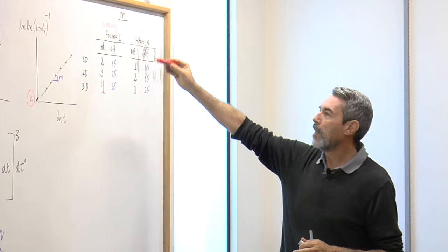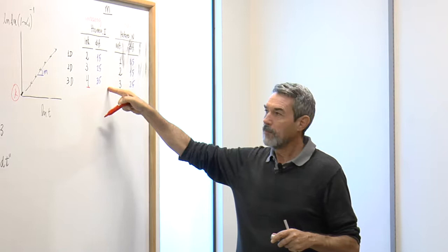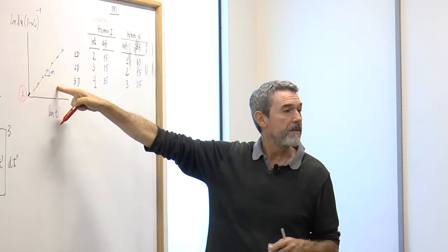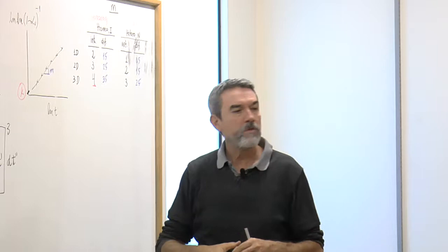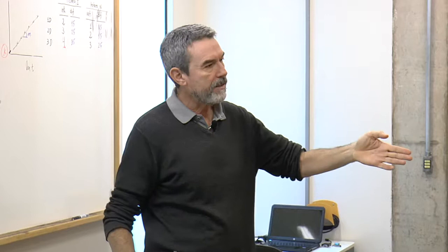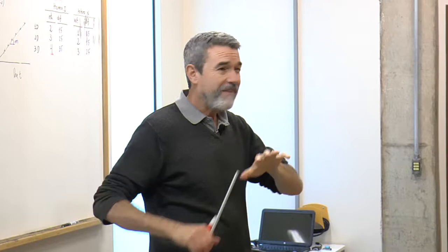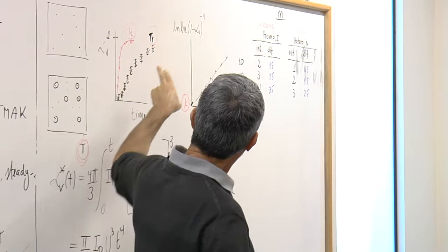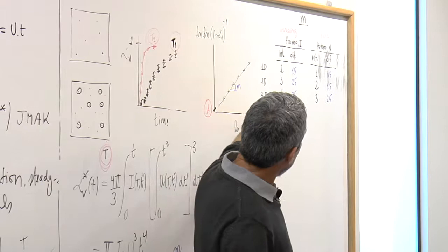So people use this table to evaluate or to analyze their experiments. Like Maziar and Mina, you are working with two different non-stoichiometric materials. You are working with enstatite glass ceramics. Mina is working with a lithium metasilicate glass ceramic, which has many other components, five or six other components. This is a nice way to analyze. At some stage, you have to measure the evolution of the volume fraction crystallized, linearize, and see what type of M you end up with.